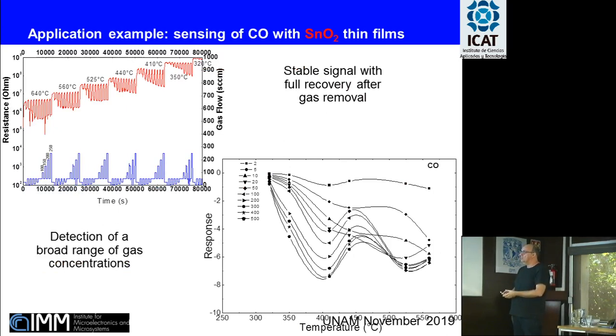This is the detection of carbon monoxide by tin oxide films, the films that I have been showing a couple of slides ago, which were giving a very reproducible and stable signal at various operating temperatures in presence of various carbon monoxide concentrations. So we could get a complete calibration curve concerning the detection of carbon monoxide, the development of gas sensors for carbon monoxide by our devices, starting from the old idea, the early idea to use alternative precursors to metal alkoxides.